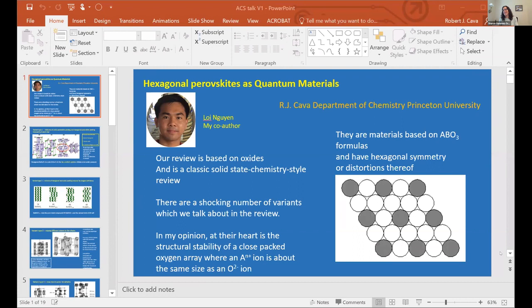My student Loi and I wrote a thing about hexagonal perovskites, and they're very important, well, they're unsung yet in oxide materials, but I think they work for a chemical reason. Basically, hexagonal perovskites work because hexagonal closest packed layers are very stable. And you learned when you were children that hexagonal closest packing is good. So suppose you could have a positive ion that was a good fit in a negative ion close pack layer. I think that is a remarkable thing, and in the periodic table, where there are lots of remarkable things, this happens to happen with barium and oxygen. If you have a different kind of non-metal making a close pack layer, it might be something else.